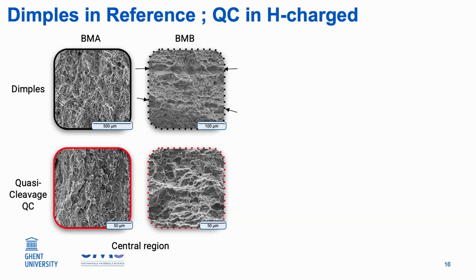As expected, when we zoomed into the central region, because that was the most interesting part, we saw that for the reference condition, there was extensive microvoid coalescence. And even BMB showed traces of the segregation bands. For the hydrogen-charged sample, a more characteristic quasi-cleavage kind of fracture was seen.